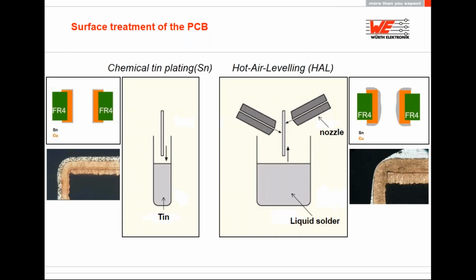And here in the images, you can actually see very clearly the difference between these two methods. So with the chemical tin plating, you can see that the thickness of the plating is very constant, very well done over the whole surface that wants to be plated. Now with the hot air leveling, the surface is not evenly plated. So you might see concentrations of the plating, smaller on some parts than others. So we actually recommend the chemical tin plating for the press fit process because it provides a better surface.